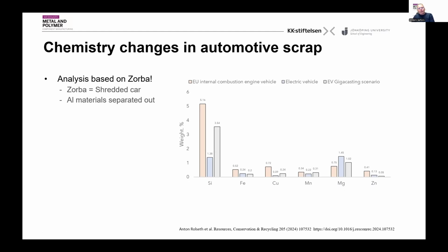Now, this is what comes out as Zorba. But if you look at the cast alloys, which is then the downcycling part, they would typically have maybe 10% silicon. And that means that you need to add silicon. And typically, if you take data from our recyclers, 20% of the energy that goes into recycling the material and making it from the Zorba scrap into the cast alloys is the addition of silicon.